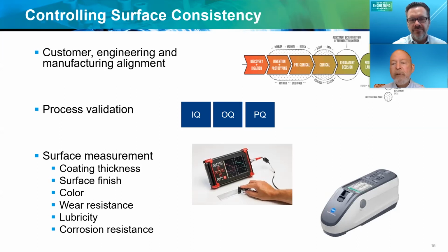And when it comes to wear resistance, there's different wear testing that could be done to a product, but normally a referee method is used where a sample is run with the product so that the wear resistance testing can be done on a panel. The Taber testing, Suga testing, these are some of the different names of tests that are out there in the metal finishing industry. Lubricity, when that's required for making sure the part doesn't get stuck and it continues to function freely, can be tested with coefficient of friction. This can be done on the actual product itself or on a referee panel.